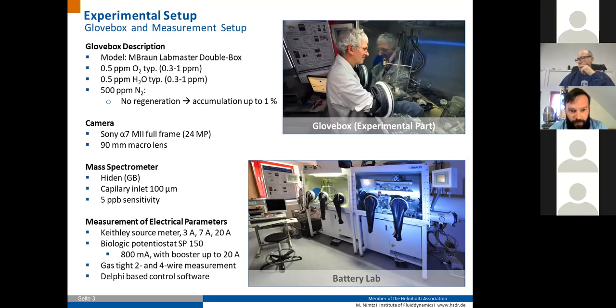The electrical connection of the cells is done via several Keithley source meters available in several current intensities from 3 up to 20 amperes. And we also have a BioLogic potentiostat, which can be used up to 800 milliamperes, with a booster up to 20 amperes as well. All experiments are done with a 2 or 4 wire measurement to have a very good sensitivity in terms of voltage, and the measurement is completely controlled by our own software programmed in Delphi by Steffen Landgraf.